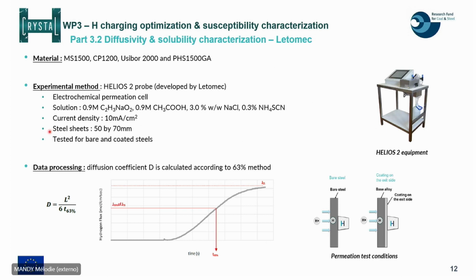The different conditions that were used are given here. I will not enter into the details, but the principle is the one that is highlighted here. You put hydrogen on one side of the material, you detect which amount and in which time it will arrive to the other side, and you have a graph like this one with the hydrogen flux as a function of the time. The diffusion coefficient, which is here the D in the equation, is defined based on a method that they have chosen, which is found in the literature, as a function of the time required to reach a certain level of the regime flux of hydrogen diffusion through the steel.